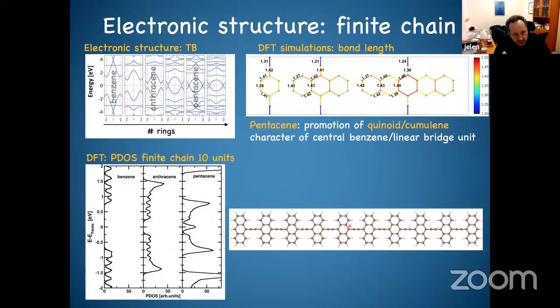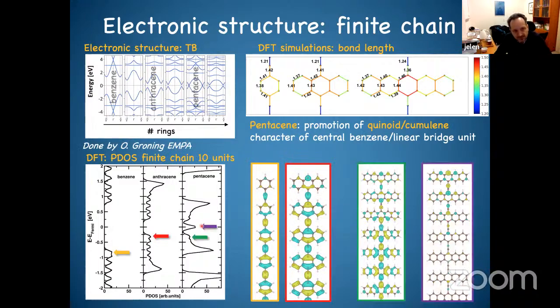And importantly, I can also do the calculation for the finite system. And what you will see is that for this benzene and anthracene polymer, which is seen here, there are no states in the band gap. But for this pentacene, I already start to see states in the band gap. And here I have to admit that this is a DFT calculation without spin polarization, but that's more instructive. But again, for this pentacene, I will start to see these edge states in the band gap. So very localized states appear in the band gap, localized only on the edges. Here I'm plotting the wave functions of the polymers, and this is the conduction band and valence band, which are spread out over the whole system. And then in this particular one, it's localized at the end. Okay, so that was kind of crazy theoretical.